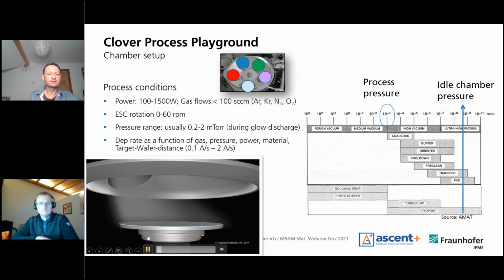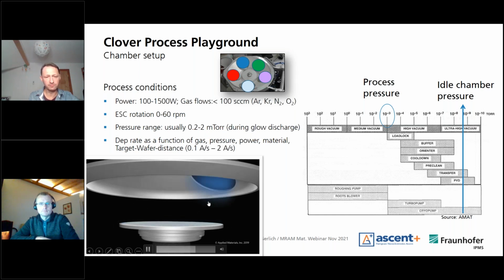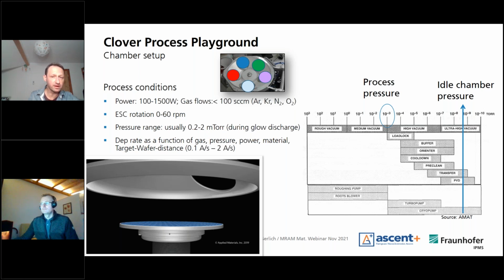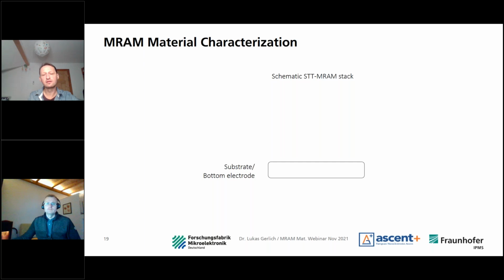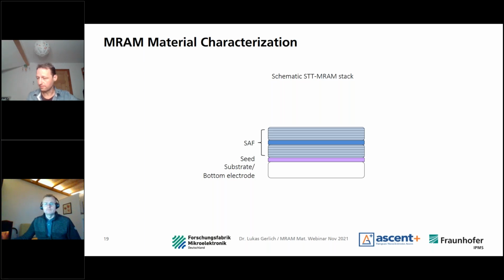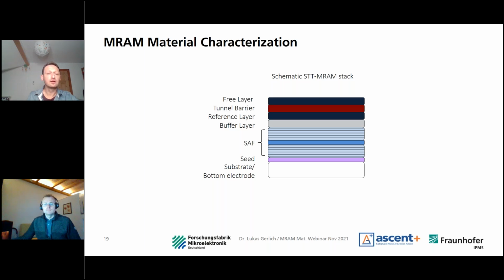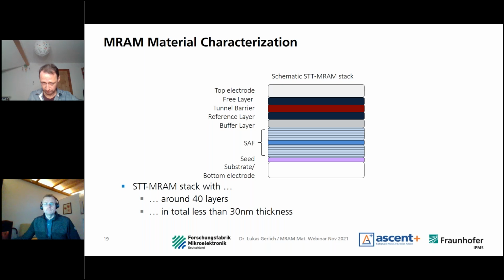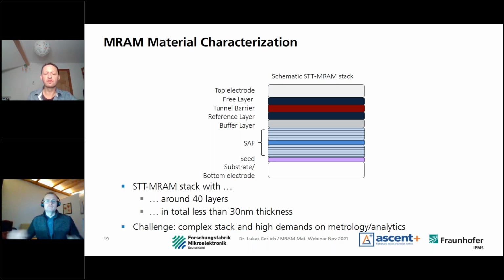During deposition, it looks like this. This is a picture from Applied Materials: the wafer is rotating and the targets are selected by this rotating hole shield. So it can be deposited without breaking the chamber vacuum or moving out of the chamber itself. And then you can deposit, without breaking the whole vacuum, a substrate, a seed, a synthetic antiferromagnet, the buffer layer, reference layer, tunnel barrier, free layer, and the top electrode. So we can deposit a stack with more than 40 layers in less than 30 nanometers. And the challenge here is to design the complex stack and fulfill the high demands on metrology and analytics.